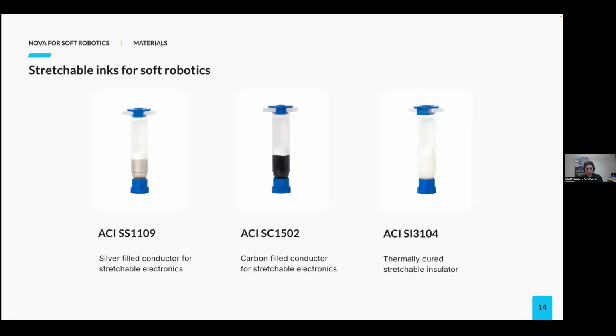ACI's SC1502 is a carbon-filled conductor, again for printed circuitry and devices on substrates like TPU, stretchable substrates. It can be dried at low temperature, so it's good for accommodating more sensitive substrates and devices. After curing, it has good conductivity and offers excellent elongation and flexibility. Again, it's been formulated for use specifically on thermoplastic urethanes or TPU, and it's specifically useful for printing over silver layers in sensor applications, again, to limit silver migration.